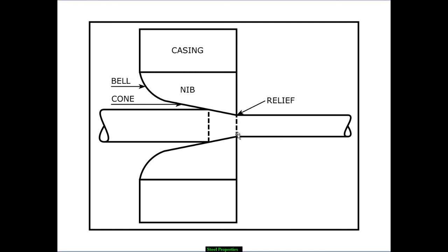The material is actually smearing and being work hardened. So in other words, planes of iron atoms are flowing by each other, and then they get snagged on carbon atoms, and then some other planes move, and eventually so many dislocations are jammed full of carbon atoms that you end up with a really hard, strong, brittle material that won't tolerate any more drawing because it will snap. The end product of this is what we used to call piano wire, then we called it aircraft cable, and now we just call it high strength wire, because basically it has become much more common in its applications, and it's not specific to any application like pianos or aircraft.